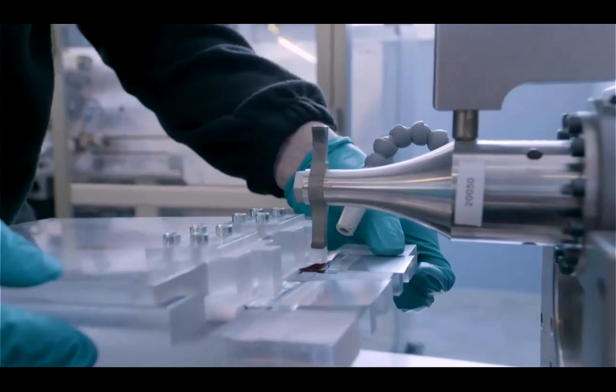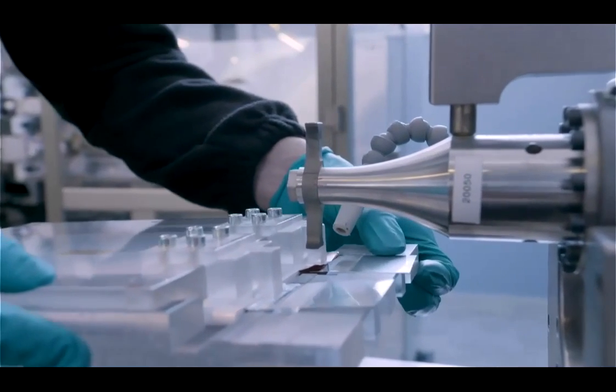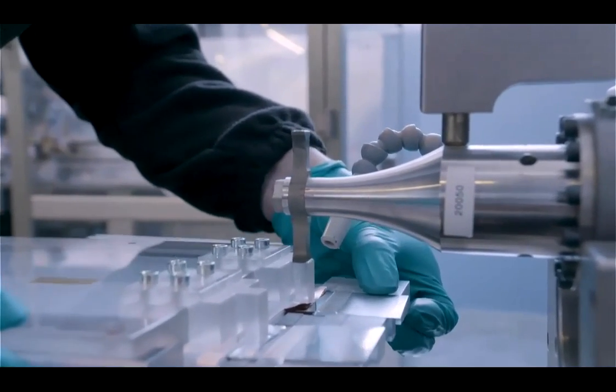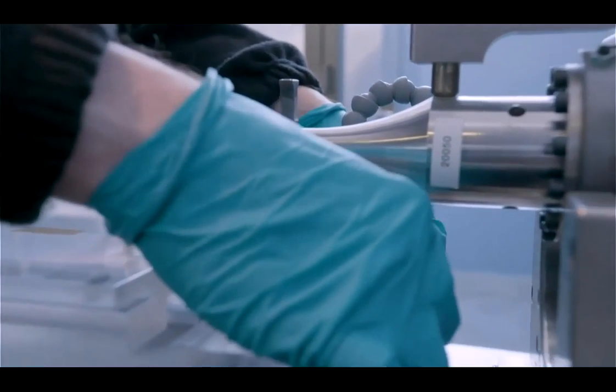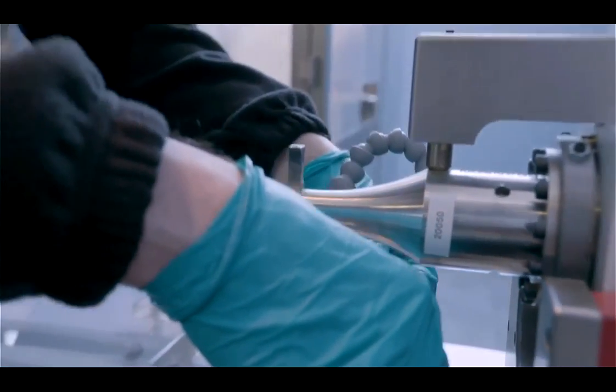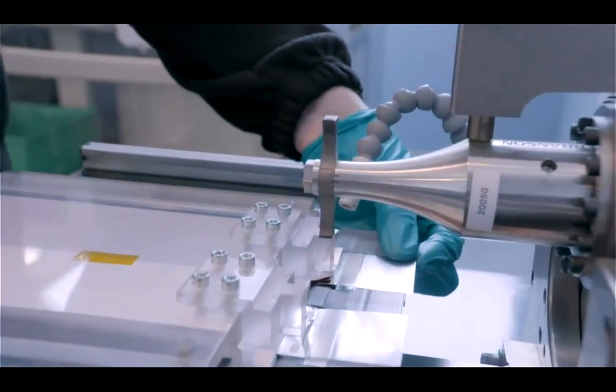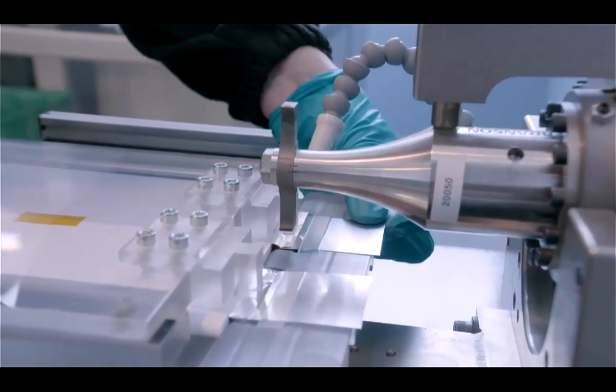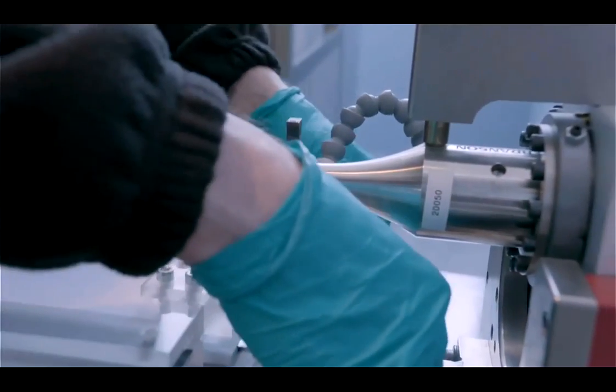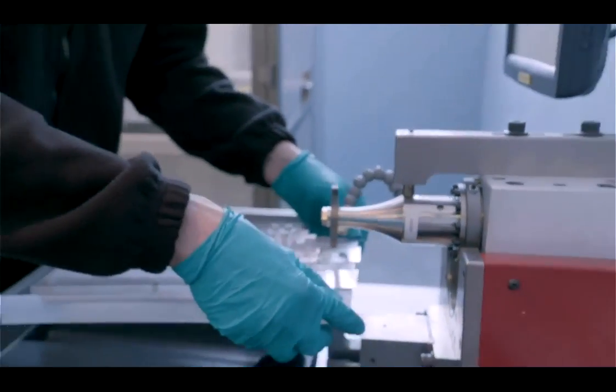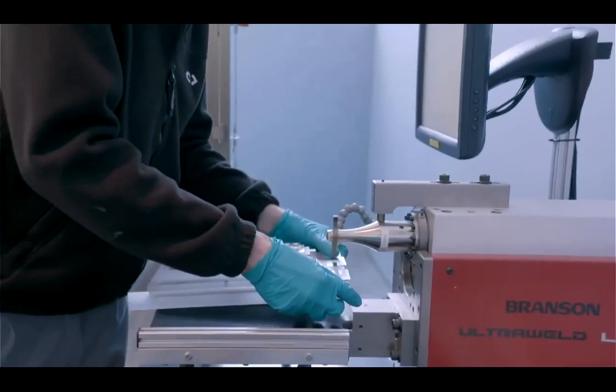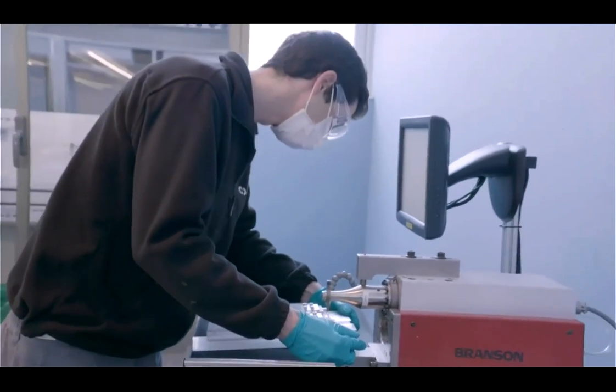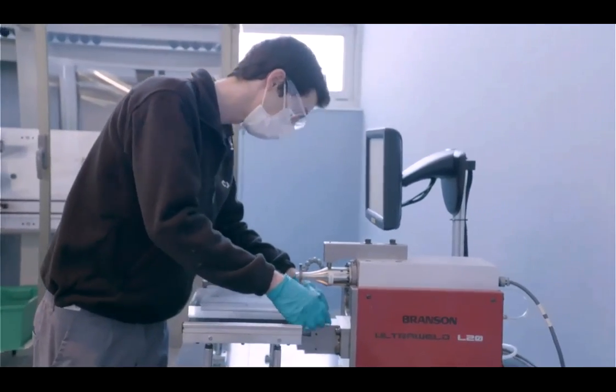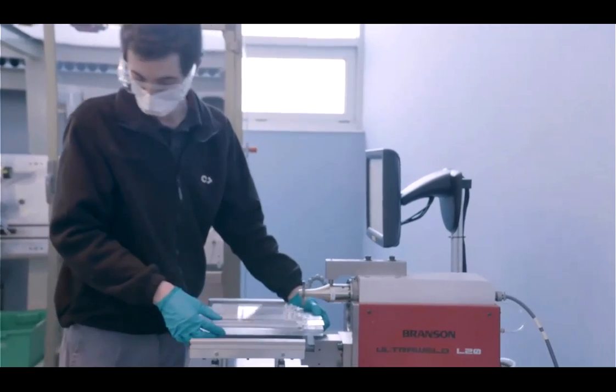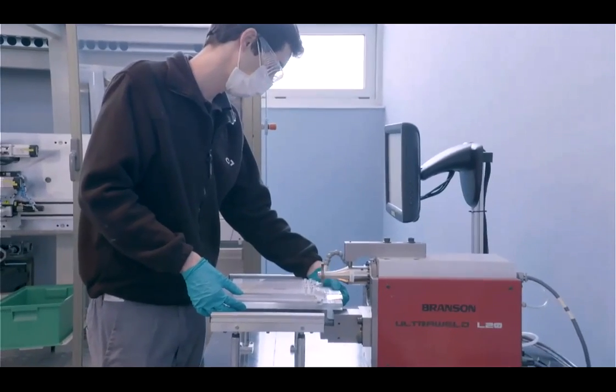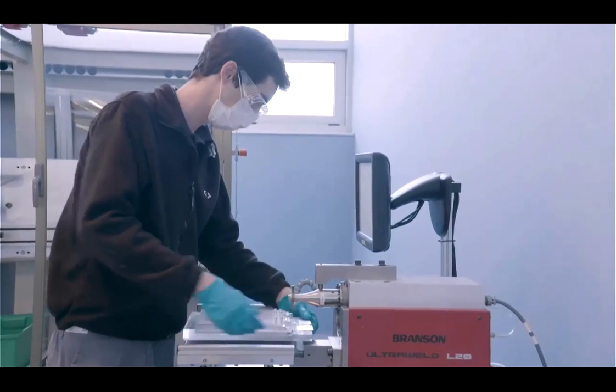Now in the image, you are seeing a transparent film over there. This is an adhesive tape that will be used in the next process to seal the cell. This is actually a very critical point, because if there is a leak of electrolyte, in general, it comes from this point. So it's important to seal the cell very, very well at this point.